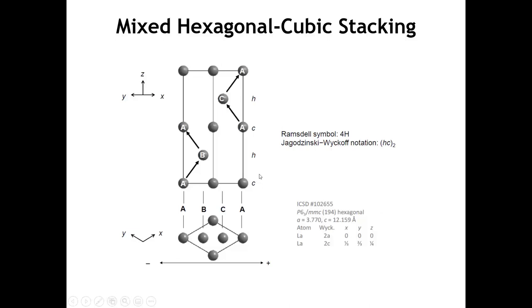Now, it may not be that obvious to you why we're calling some layers hexagonal and others cubic. And the way we can distinguish those two is here you can see that this layer, the second layer in the unit cell, is denoted as a hexagonal layer. Why is that? That's because the sequence is ABA. So the layer above and the layer below are both an A layer. And that's exactly what you would get in a hexagonal stacking. ABABAB. Every B layer would have an A above and below it. On the other hand, the middle layer here we're calling a cubic layer. And the reason for that is because the layer above and below are different. This goes BAC. So the A is sandwiched by a B layer and a C layer. And because they're different, we call that a cubic packing layer.